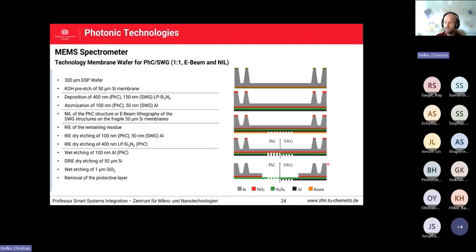Based on the wafer preparation flow shown by Carla before, we have to ensure that our technology integration process goes in parallel with the wafers which Carla mentioned, so that we do not have to realize completely new integration processes. So the main wafer flow of the freestanding membranes is nearly equal to the one shown by Carla. We also started here with 300 micrometer thin double-side polished wafers, where we etch a 250 micrometer cavity into the silicon from the backside. This is a batch process, and so we save a lot of time up to the final release of the membrane.